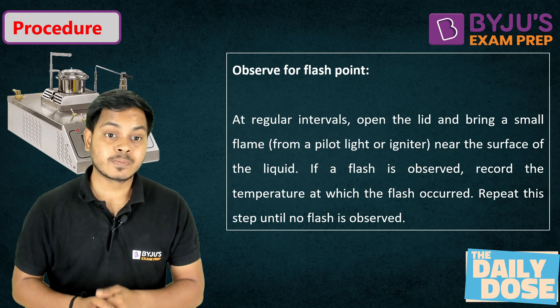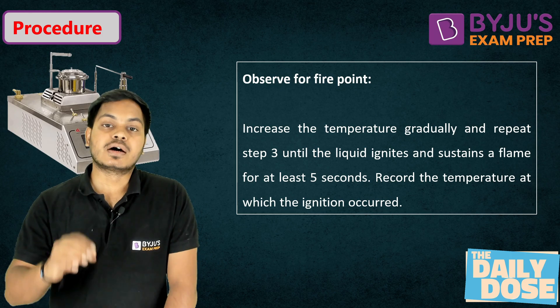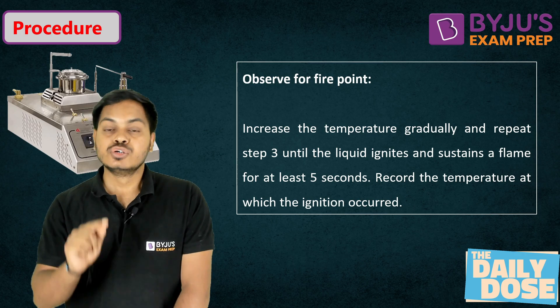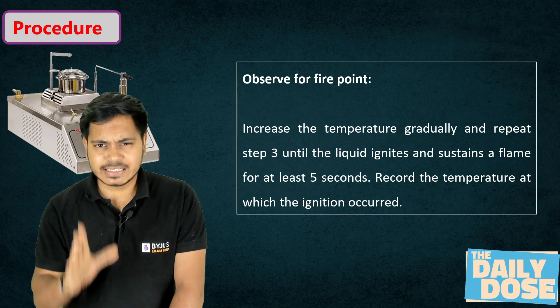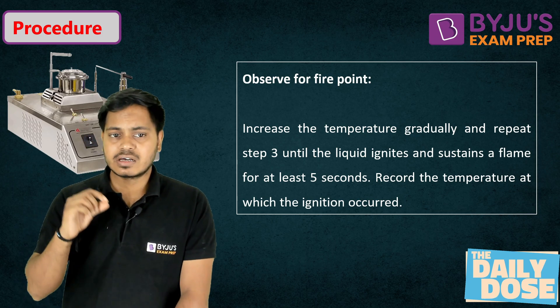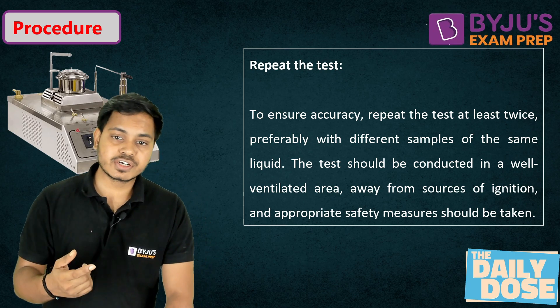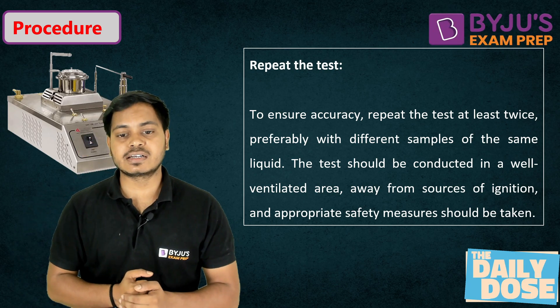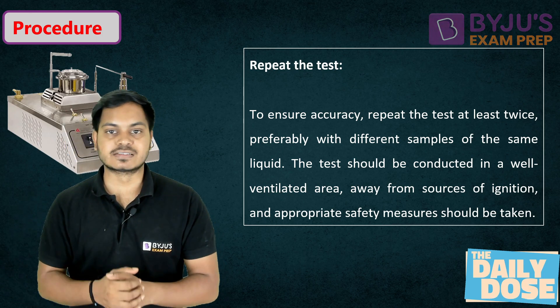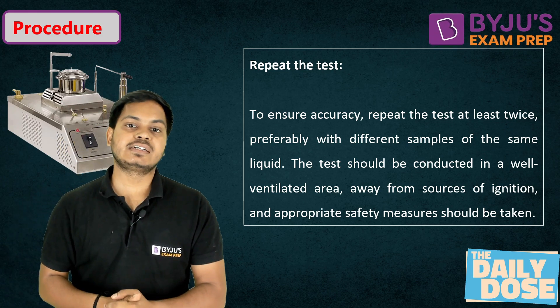After recording the flash point, continue increasing the temperature until the surface of the bitumen itself catches fire, and that fire sustains for at least five seconds on the surface — this temperature is called the fire point. The entire test is repeated at least twice to obtain more accurate results.